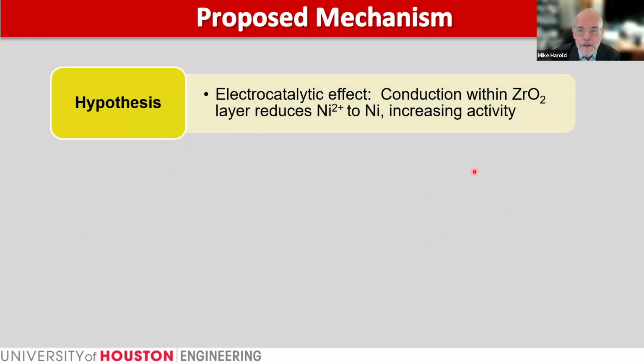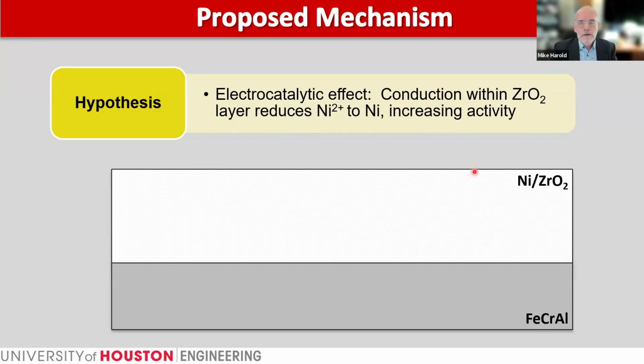We believe what's happening here is an electrocatalytic effect. In essence, conduction within the zirconia support layer serves to reduce nickel cations to nickel metal, increasing activity. Now, that statement implies the fact that it's known in the literature that reduced nickel, instead of, say, nickel oxide or nickel hydroxide, is more catalytically active for SMR than is the oxide or hydroxide. So we're hanging our hat on that known fact. Now, let me walk you through what we think may be happening.